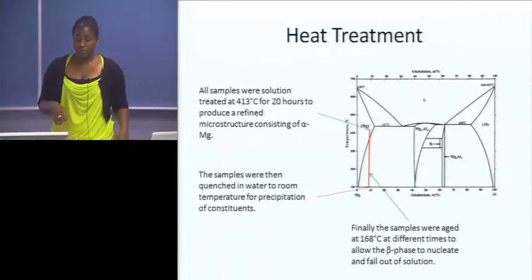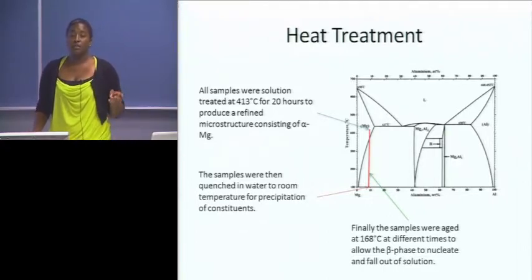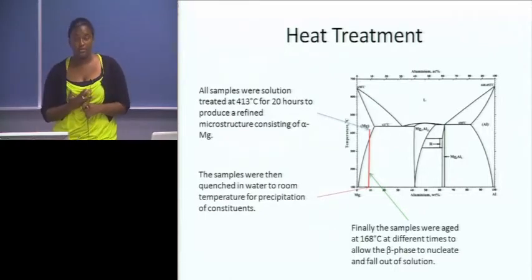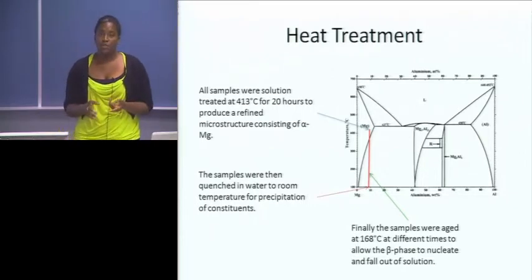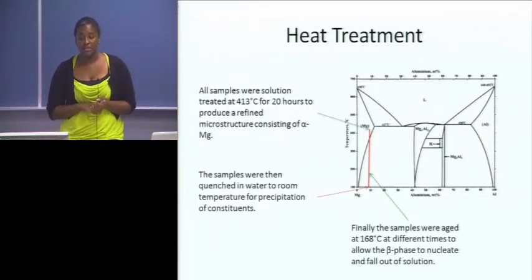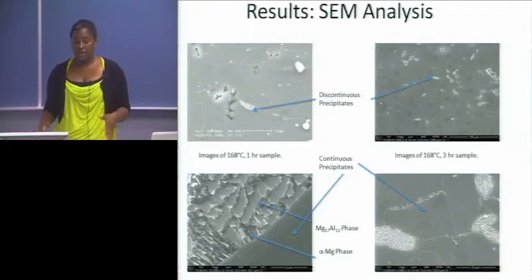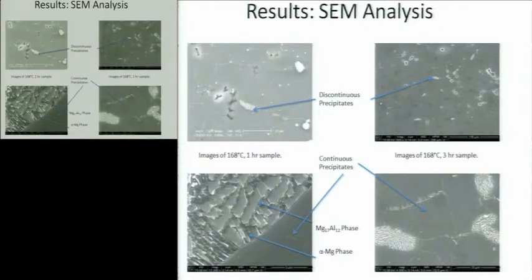compounds. So what I did was, after I did all of my heat treatments, I characterized the precipitates using optical microscopy, SEM, and then I looked at the mechanical properties using micro hardness and tensile strength testing. So if you go to this slide, you can see the microstructure of the 1 hour sample. So you can see that there's a small amount of discontinuous precipitates in both the 1 hour and 3 hour sample, but there are more discontinuous precipitates in the 3 hour sample.